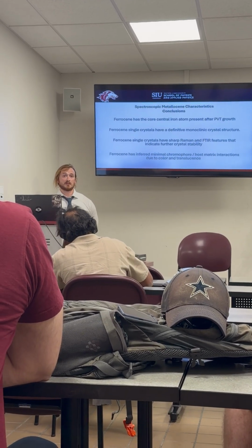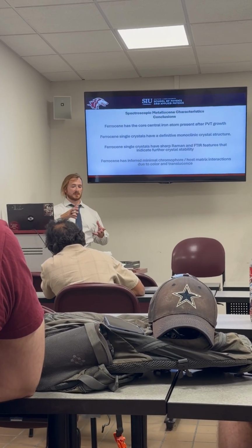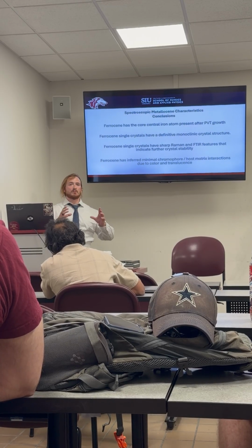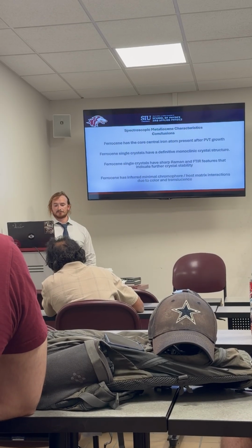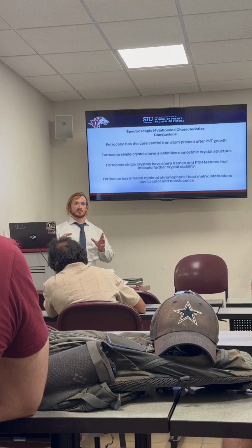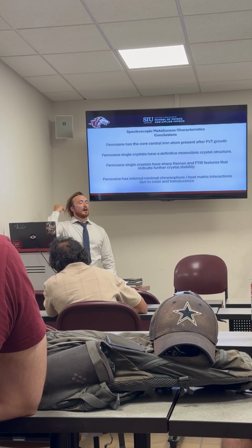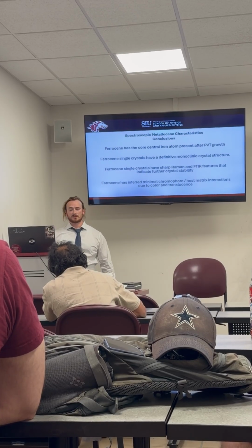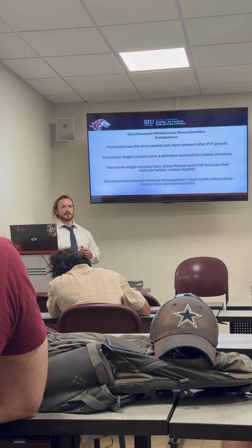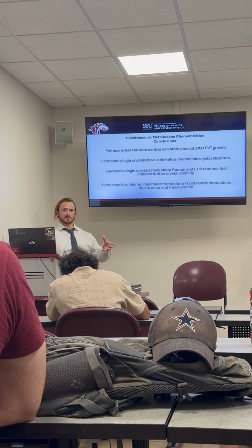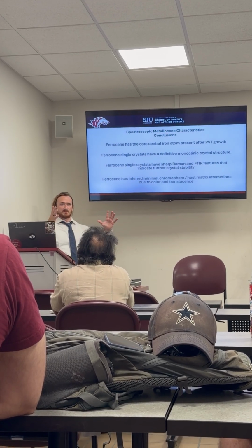What's a vibrational mode? A vibrational mode is allowed depending on how that crystal or molecule is constructed. There are only certain allowed modes because of the symmetry of that crystal. So you can have forbidden symmetries, which say that you cannot have that vibrational mode. So kind of glossing over, the FTIR and the Raman will show what allowed vibrations are in the crystal, and you can do a little crystal inference on the crystal structure. So if you have stronger peaks, it means it's tighter; more broad peaks, it means more vibrations are allowed.